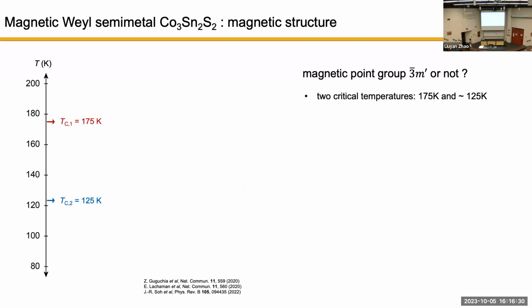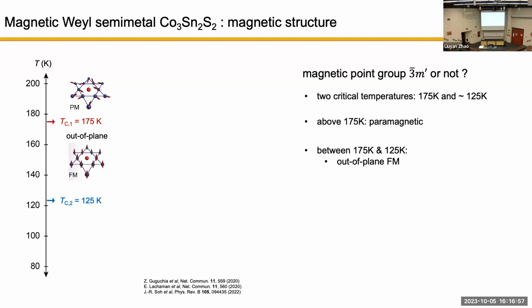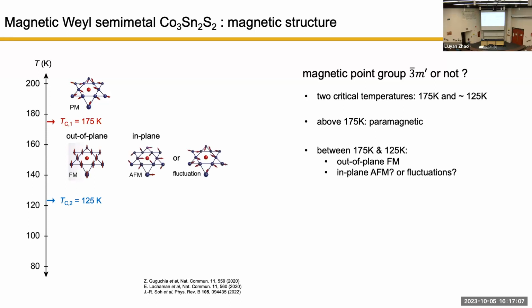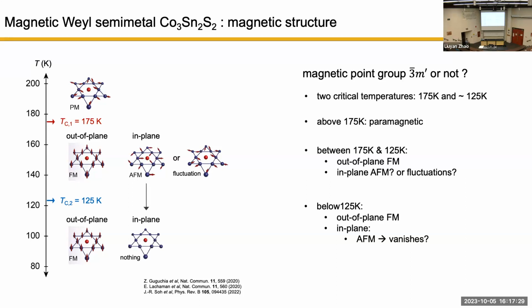Okay, so there are 2 critical temperatures being raised in the field. One is 175, the other is 125. So what's interesting about this compound's magnetism is that you have to think of the out-of-plane spin moment and the in-plane spin component separately, which is not common for many magnetic materials. Many magnetic materials, I just think the spin one direction, that's enough. Here, think separately. So separately thinking, below this 175, the out-of-plane component is going to order ferromagnetically. That everyone agrees. What people don't agree is how the in-plane component works. So there are people saying, right below this one, it's already an antiferromagnetic order. Other people say, no, below this one, your in-plane component is dynamically fluctuating. Okay, and then below 125, the out-of-plane component still has no doubt ferromagnetism. In plane, someone says, no, your in-plane component all got pulled into the out-of-plane direction. It's just a very simple ferromagnet with out-of-plane spin.